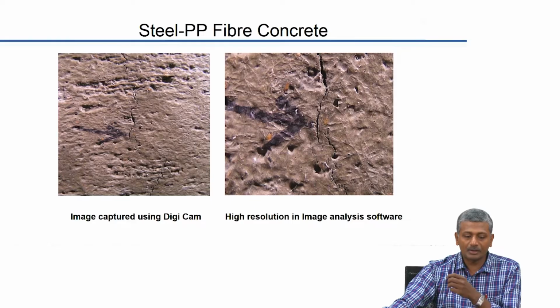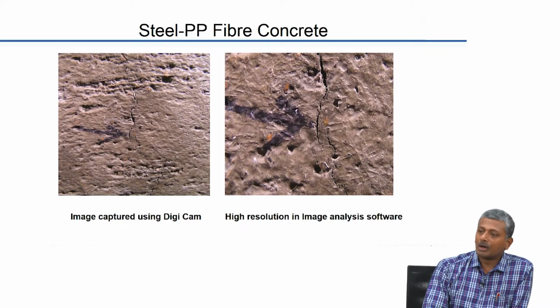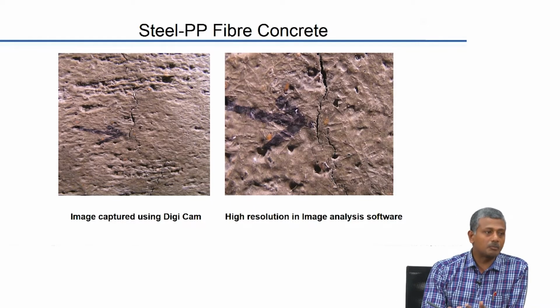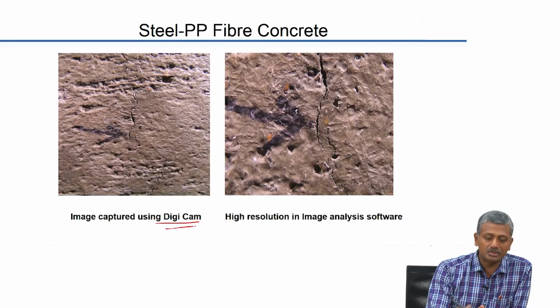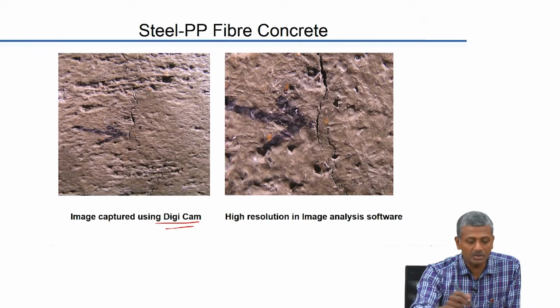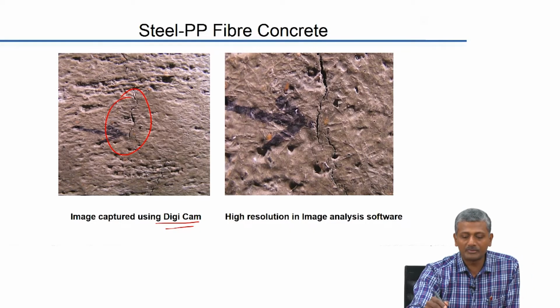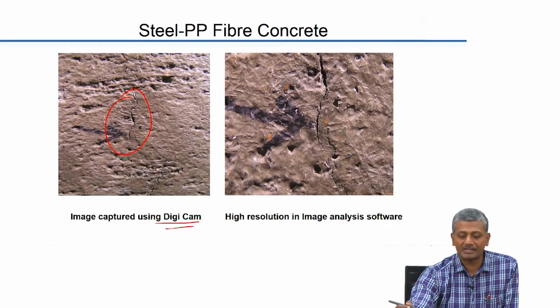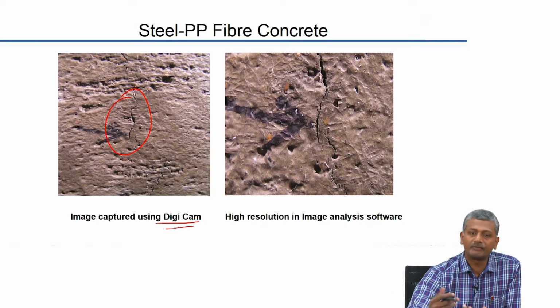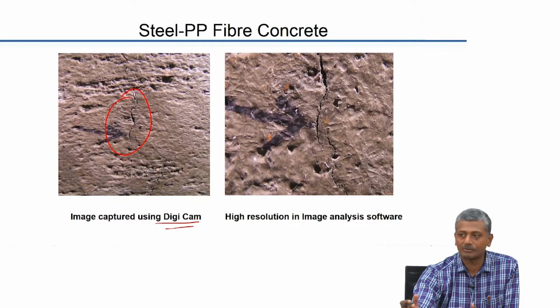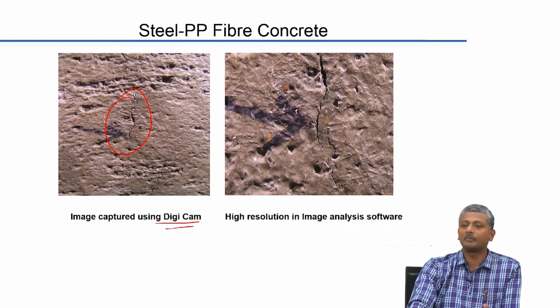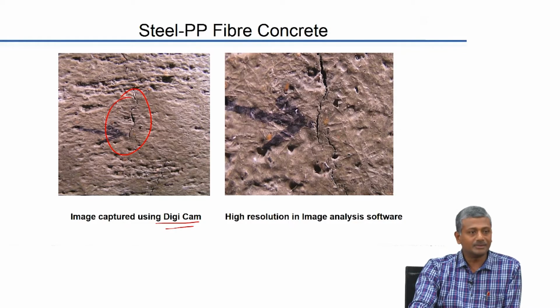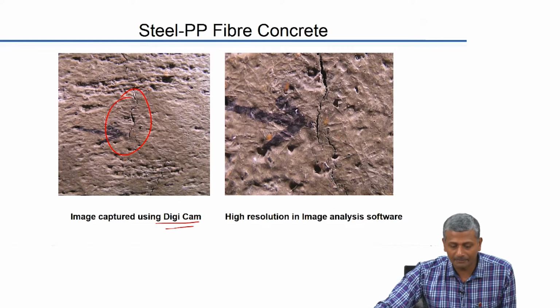So, again here there is a combination, so how we actually captured the images and how we processed the images to ensure that we were able to extract the data related to cracking. This is the image as captured using a digital camera, and this is the same image, a zoomed-up section, where the image has been enhanced with the help of image analysis software. Of course, it requires some level of expertise and experience handling these types of software, but essentially what we want to do is get a sharper image so that we can track the progress of cracking much more easily.